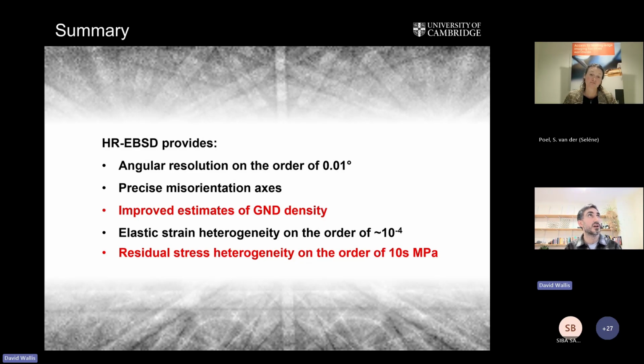There's also, more generally for HR-EBSD, I've presented the traditional way of doing HR-EBSD, where you get these little sub-regions within the pattern. But there are people exploring new ways where you fit the distortion of the whole diffraction pattern at once, which has some pros and cons, or using simulated patterns as a reference rather than using a different pattern from within the sample. And again, that has pros and cons. So there are different directions that the technique is going in, but at the same time, we've already got this established methodology that works very nicely, and there's a whole range of directions we can take it in to apply it to different geological problems. So you're only just starting, as I understand it. Yeah, that's right.